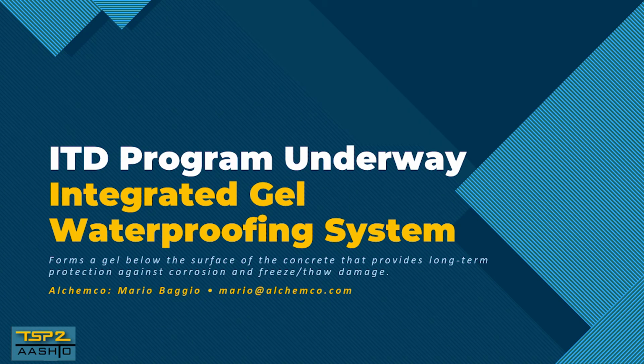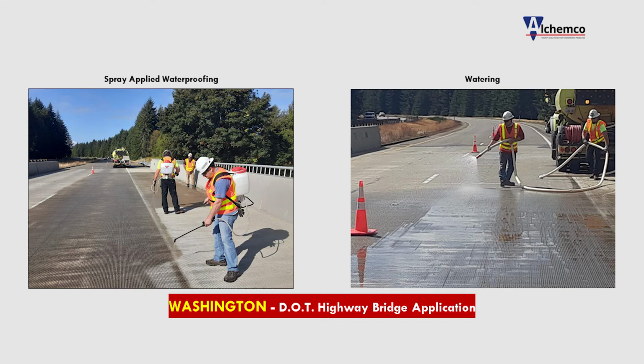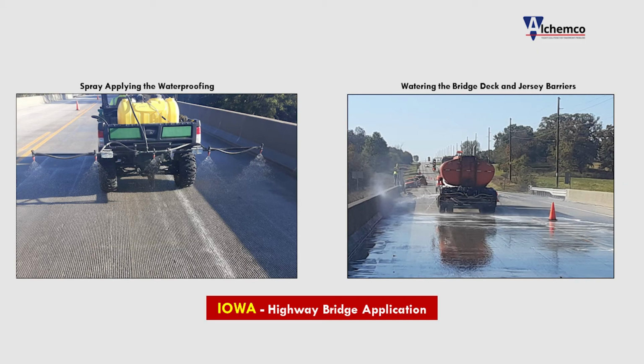And we have the integrated gel waterproofing system from Alchemco. This is a long-lasting waterproofing product with a few unique abilities. One of them is the reapplication period of 25 years. Often when we talk with DOTs, they are concerned about lane closures. So it's a very fast product to apply. You can close a lane for just a few hours and do the application, and you don't have to go back to this bridge for over 20 years, or 25 years. So it's a very simple and easy application.